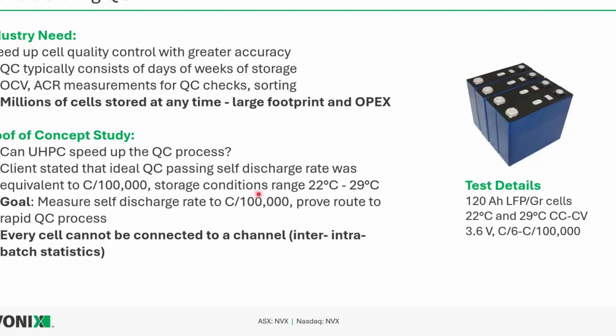However, this can be difficult because these storage conditions are in massive warehouses and the temperatures can fluctuate by plus or minus 4 degrees or so. It's very expensive to keep a very stable temperature within these large facilities. So our goal was to measure this self-discharge rate, prove out some cells that have already passed QC, and then prove a route to a more rapid QC process. This is more of a case study thought experiment than really fleshing out what could be a new QC method. Of course, every cell cannot be connected to a UHPC channel, that would make for a very expensive QC facility with millions of UHPC channels. So this would be more relevant for intra-batch statistics.